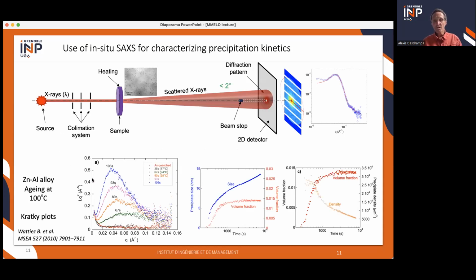Just for those who are not specialists in small angle scattering, a few words about what kind of parameters you can extract in situ. This was in a zinc aluminum alloy aged at a relatively low temperature, where you form zinc-rich precipitates in an aluminum matrix. No, aluminum-rich precipitates in a zinc matrix, sorry. And you see that during in situ heating, the scattering signal increases very, very fast, showing the precipitation sequence.